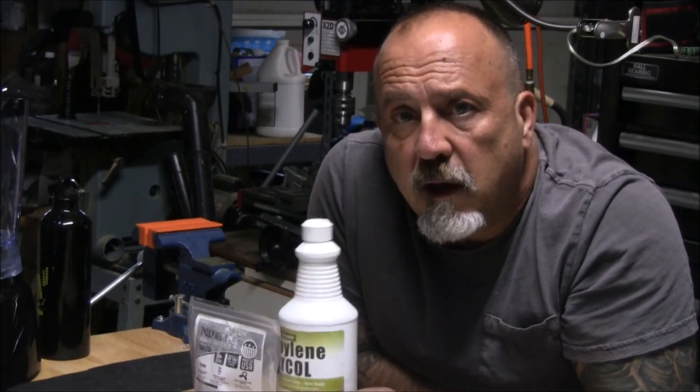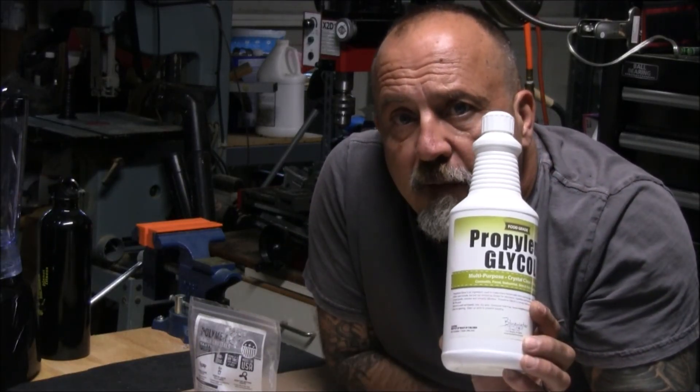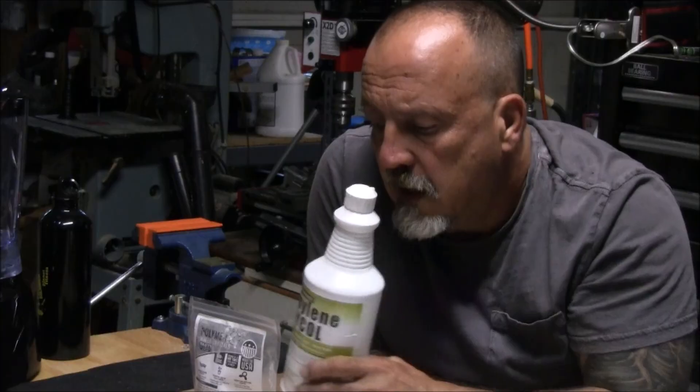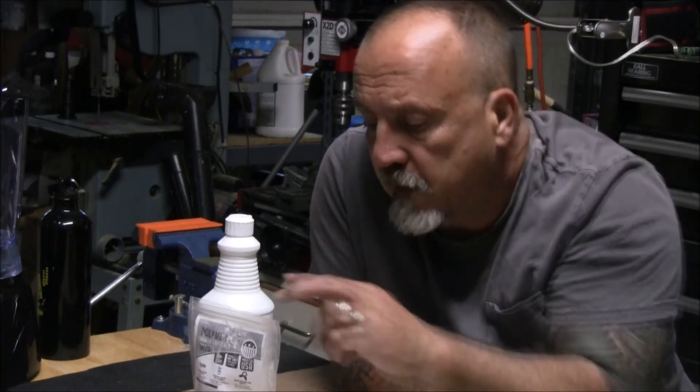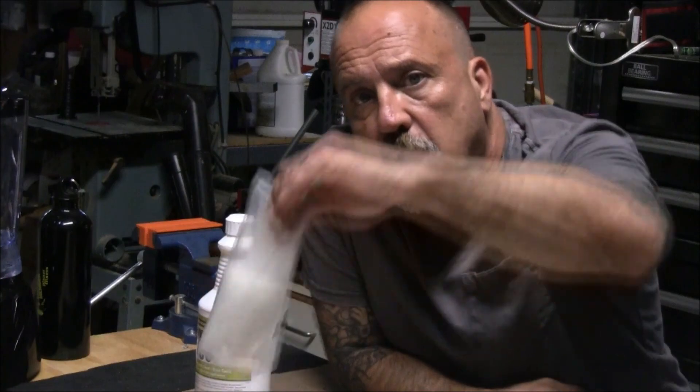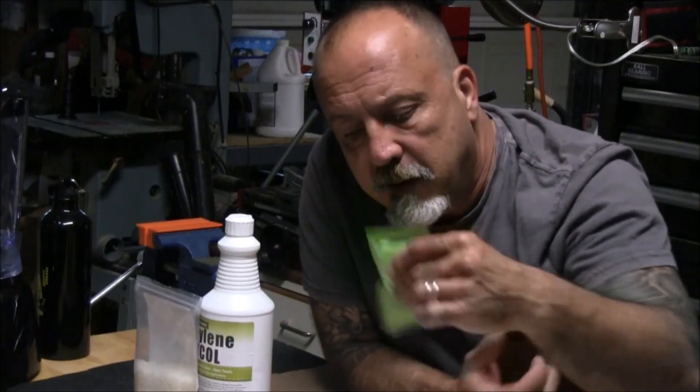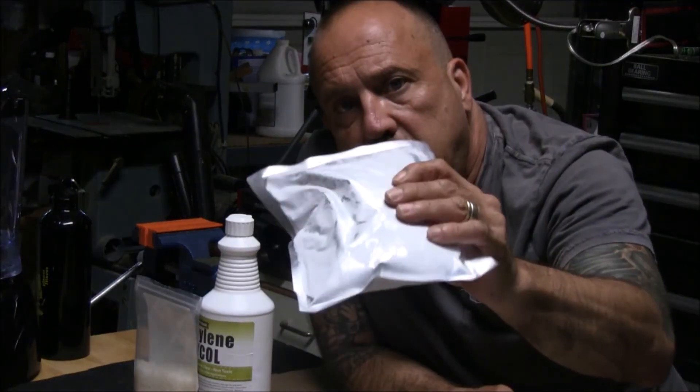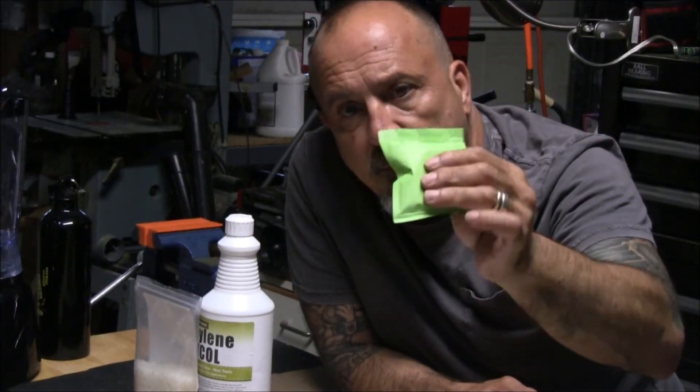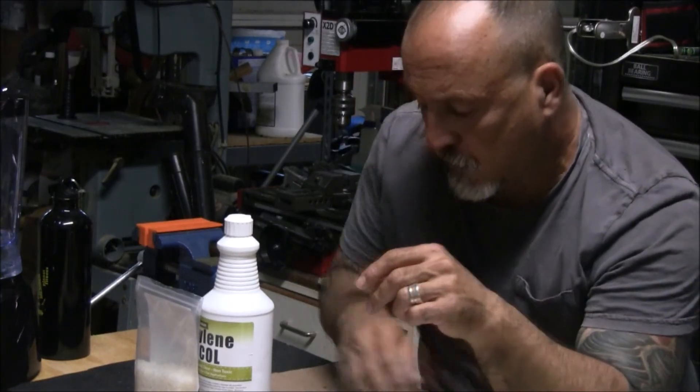So the formula as I put it together is a mixture of 10% propylene glycol with water, and then you add that to the hydrophilic polymer gels. The ratios I've been using are 50 ml of this - basically put it in a water bottle so it's up to 500 ml, that gives us a 10% PG mix - and one teaspoon of the gel crystals into a water bottle. Mix it all together, let the crystals expand - they'll soak up every last bit of that water and PG mix or propylene glycol. And once you got that, you can bag them either in these large bags (I use a heat sealer) or these small bags. Works really good, and you've seen the results - really cold, long-lasting. I'm really pleased with the results. It just took me a long time to do this, a lot of experimentation and time-lapse videos.